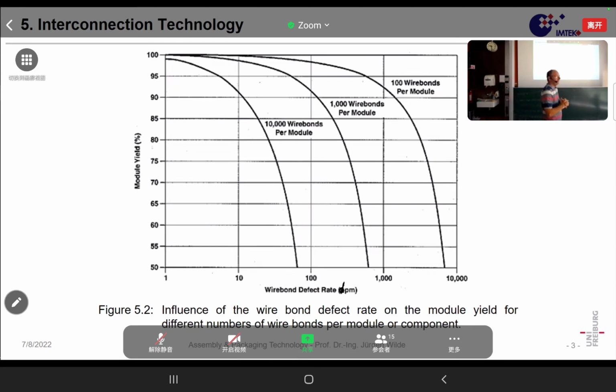If you look at individual bonds, but now you must think about, we sometimes have packages, or we have, for instance, thick film circuits which have 1,000 wire bonds, and all of the wire bonds must be okay. Or if only one wire bond is not okay, all of your circuit is not working. So that means in that case, when you have many wire bonds on your module or on your device,